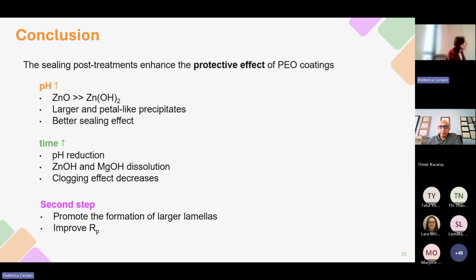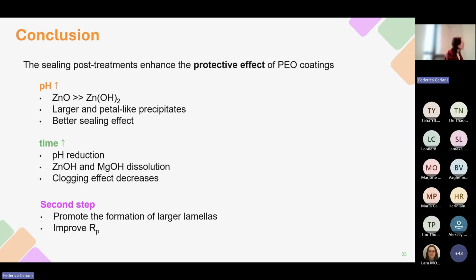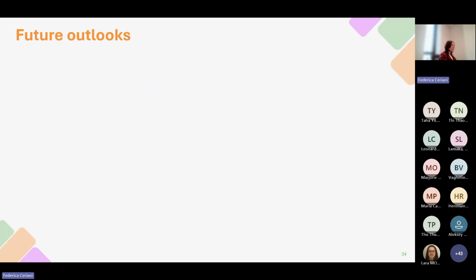Finally, when the second step post-treatment is carried out, consisting in the deposition of metavanadate ions, these promote the formation of larger lamellas that are able to better close the porosity of the PEO coating, leading to an improvement in the RP values. Finally, I would like to add some future outlooks.